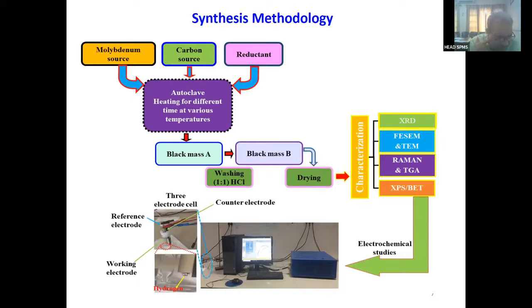So what we have done is, we need not purge the argon and other gases in order to remove the oxygen from the chamber. We have taken magnesium as a reducing element, and after putting all these elements in, we are sealing the autoclave properly. The sealing of the autoclave is important here, and we are heating it to different temperatures, something around 600 for some time, 700 for some time, 800 for some time. You have to optimize the process parameters here.